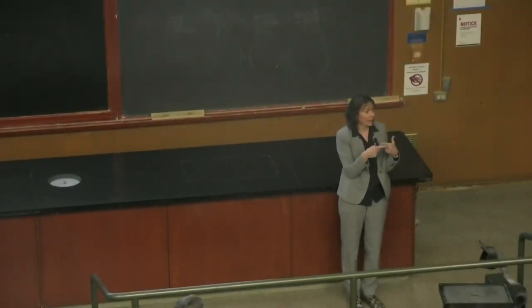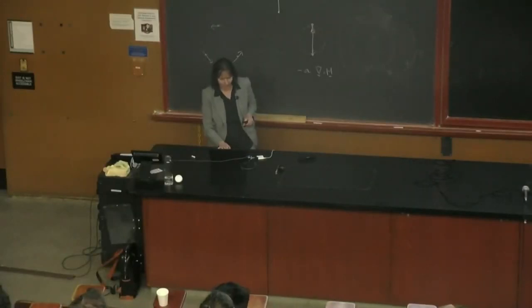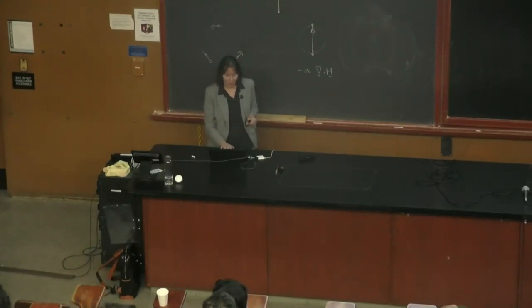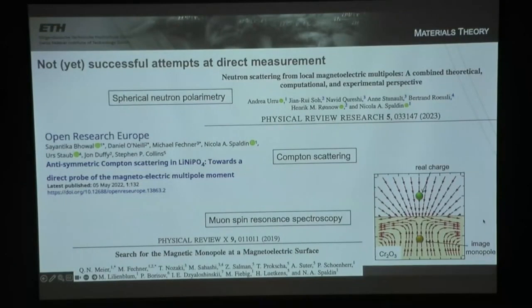But the Chern-Simons term in an axion insulator, symmetry-wise, is the same as the magnetoelectric hedgehog. So it has this diagonal magnetoelectric response. People have tried, for example, this experiment that I showed to try to measure the hedgehog structure in chromium oxide, Cr2O3. This has also been tried, this one down here, for a topological insulator, where, in principle, you can do the same experiment. The difficulty is you somehow have to break the time reversal in the topological insulator.